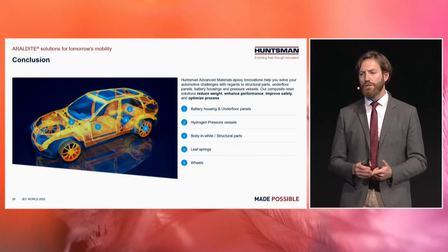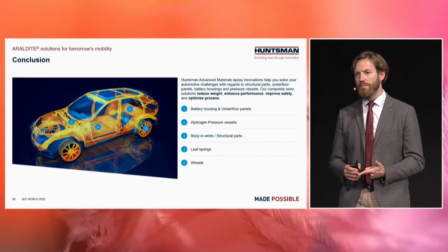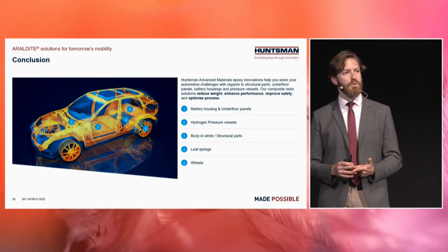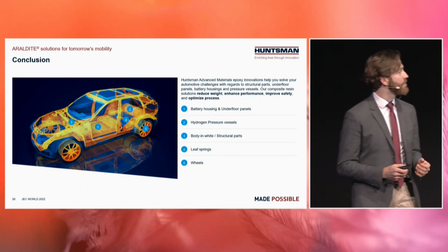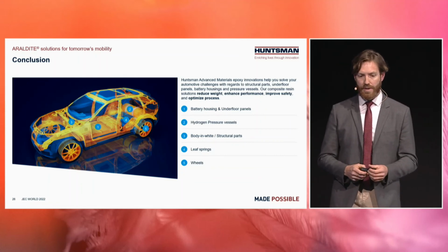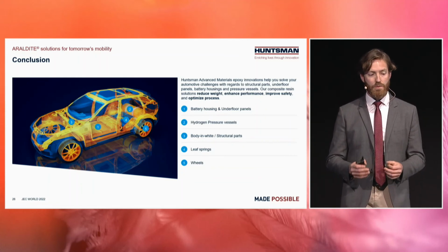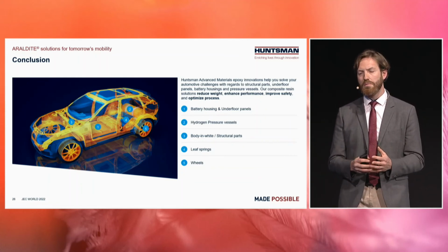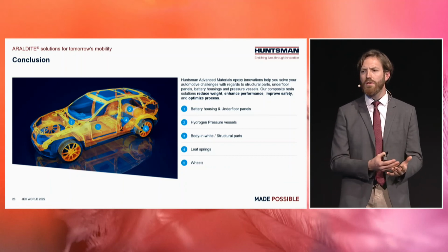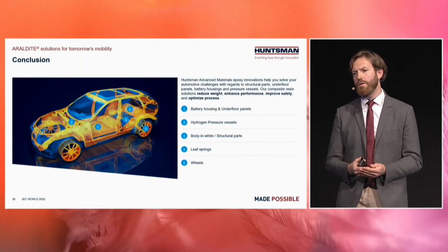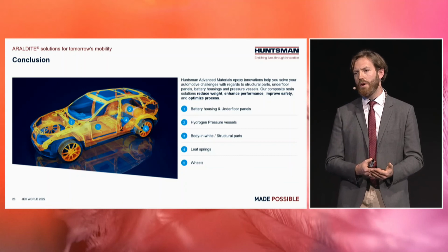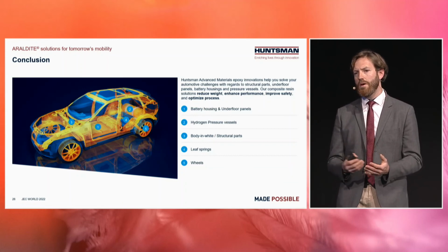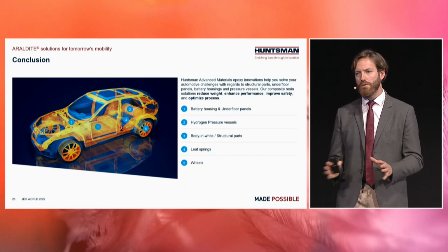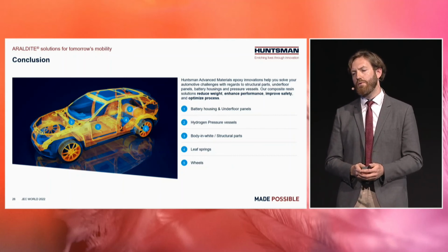For the second question about the curing cycle times, I think the fastest cure cycle times we can reach are related to the wet compression molding technology, sometimes high pressure RTM, but wet compression molding technologies. We are capable of curing in 30 seconds at 140 Celsius, and we have no post-cure at all. So 30 seconds at 140 Celsius is what we can do in mass production.